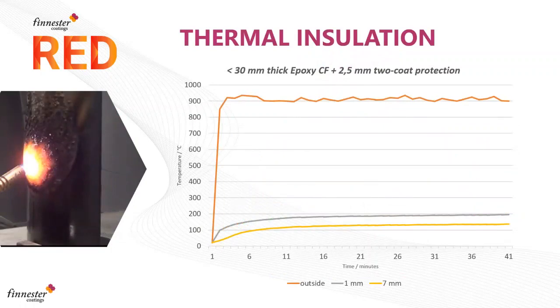This is a 40-minute burn for 900 degrees flame, propane flame, and we measured the temperature from the composite in 1 millimeter depth from the outside and 7 millimeter depth from the outside, from the flame side. And we can see that after 10 minutes, the temperatures stabilize in a composite, which is due to this ceramification effect combined with intumescent thermal protection.